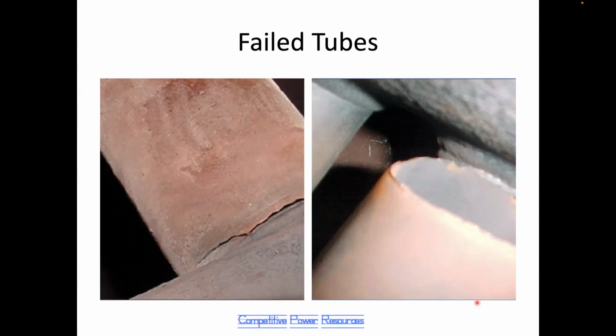We saw that crack already. Here's a severe case where if you put enough water in an overspray or leaking event into a superheater tube, in some cases it will pull the tube completely off the header. This is relatively rare, but can happen. It's much more likely you would end up with a fatigue crack.